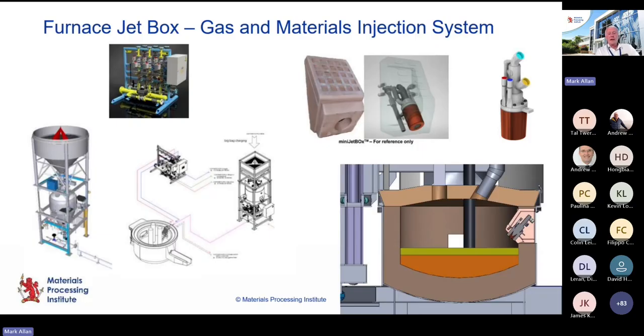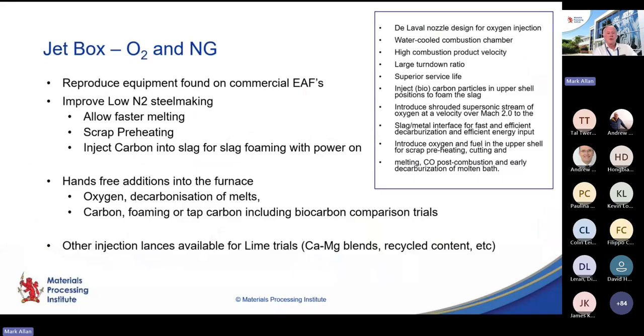And through this jet box, we can either supply additional heat through a high velocity natural gas burner, but we can also inject carbon, which could be fossil fuel carbon, or it could be sustainable carbon in various forms, such as biochar, as well as oxygen injection. And what this allows us to do, which we didn't have the capability of doing on the previous version, is various aspects which will both improve furnace efficiency, allowing faster melting, scrap preheating, but also the injection of carbon gives us a lot more control over slag foaming, which improves both furnace efficiency in terms of its insulating capability, and also helps us with nitrogen control by preventing air ingress.